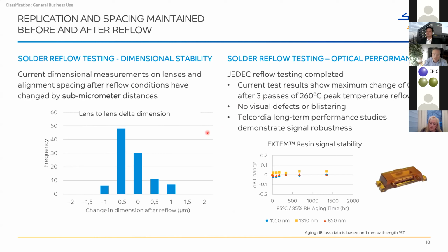Okay, that's one thing. The other thing is, of course, what about the optical performance? What about the signal loss after reflow soldering? We see that we lose a very small amount of signal, only 0.1, 0.2 dB after reflow soldering. Remember, the total signal loss budget is around 3.5 dB. That includes all fibers, all waveguides, all connections. So, I mean, 0.2 is acceptable for the customer. We also did not see any blistering or any visual defect.